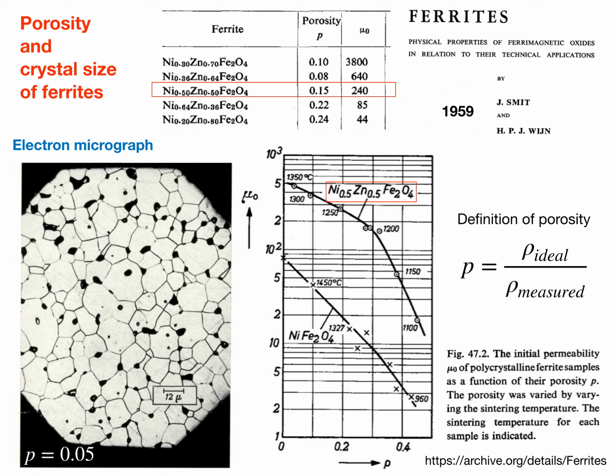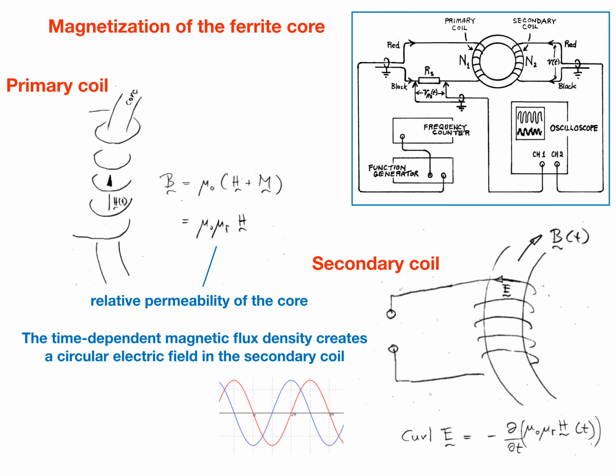It is therefore not surprising that the technical specifications for the toroid considered here specify a value of 125 for the initial permeability, which is significantly lower than the value of 240, which is quoted in this standard book on ferrites. The value of the relative permeability μr determines the magnitude of the magnetization of the ferrite core by the time-dependent magnetic field strength H created by the primary coil.